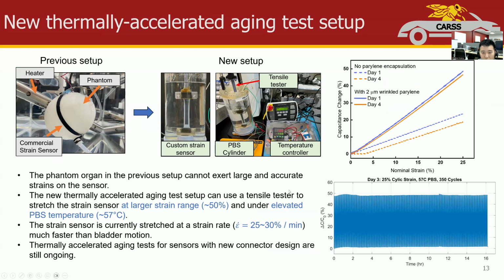To verify our encapsulation performance, we have built different aging setups. One setup used a custom-made phantom organ in which we inflate it to stretch the sensor on it, but it was difficult to apply large and accurate strain on the sensor. Another test setup uses a tensile tester to stretch the sensor directly in a heated PBS cylinder. This allows us to test the sensor at a larger strain range and faster strain rate. The test is still ongoing.